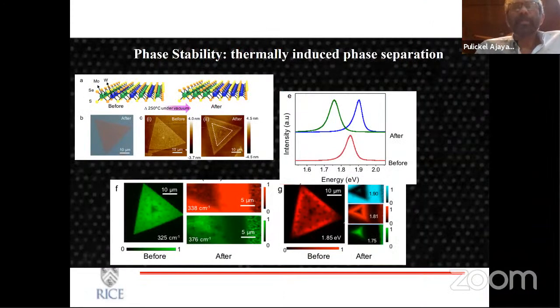So the phase stability, as I said, you could heat them. You can create these multi-component systems like this is a moly tungsten sulfur selenium alloy that you saw. And by heating, you can actually make them to segregate. Again, the idea of phase stability within 2 dimensions is really not well studied. These are opportunities for us to actually do in situ studies and so on how these lateral interfaces become unstable and how diffusion across these interfaces happen. So there's a lot of beautiful in situ electron microscopy studies that you can do with these type of systems because they undergo this type of phase segregation.